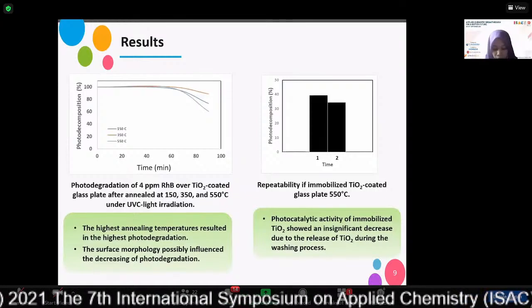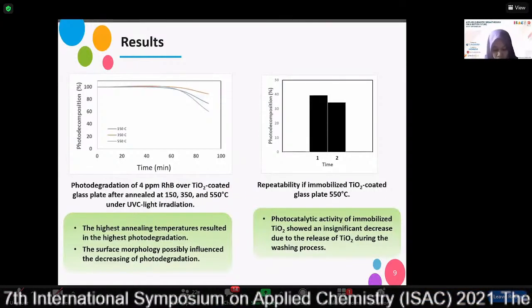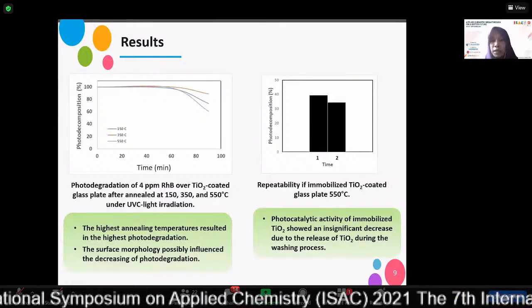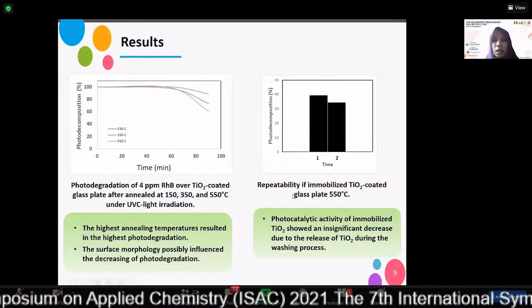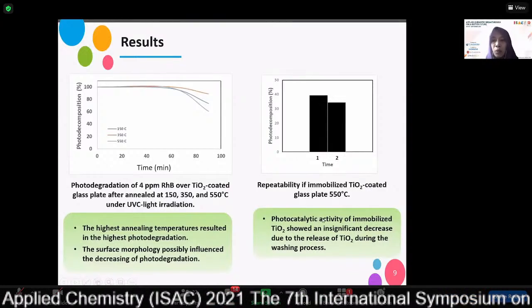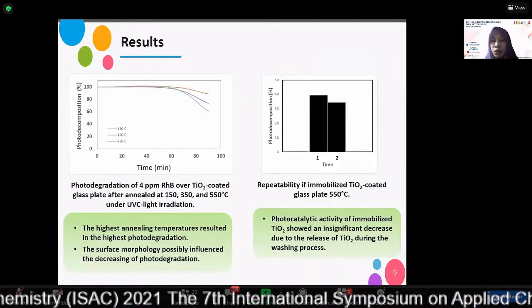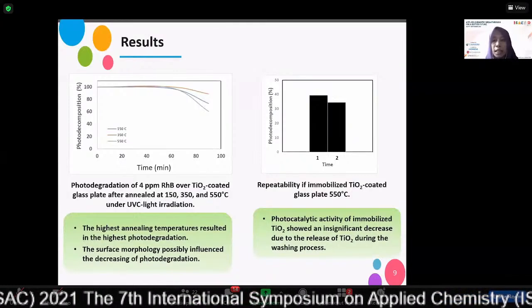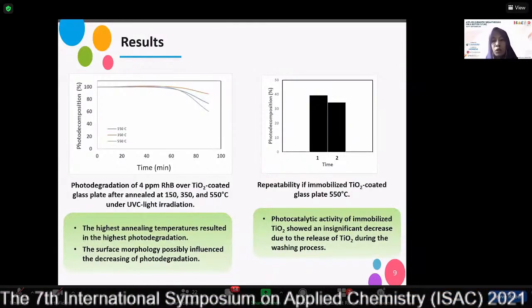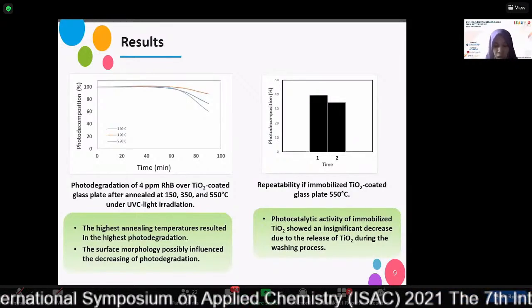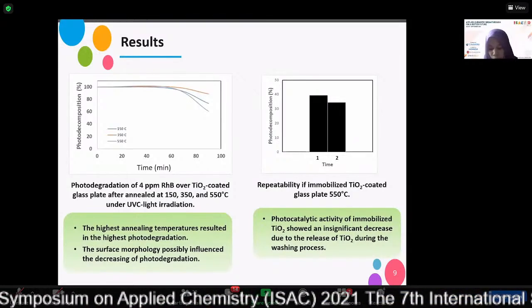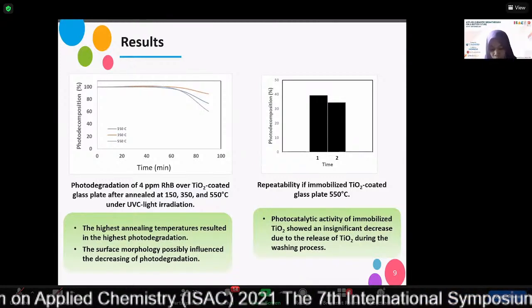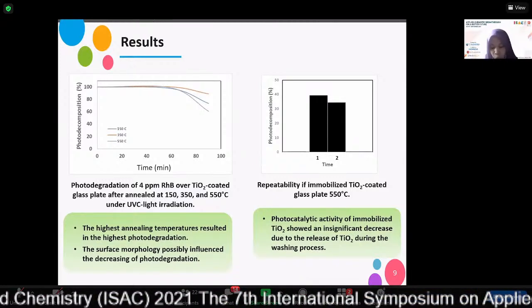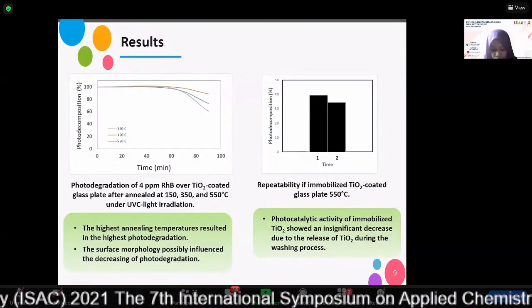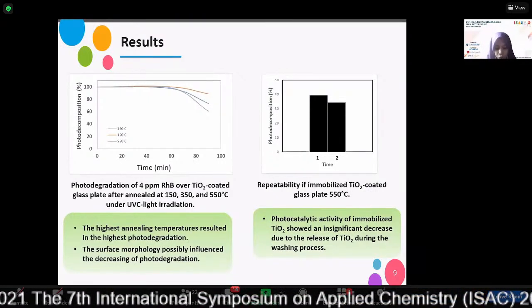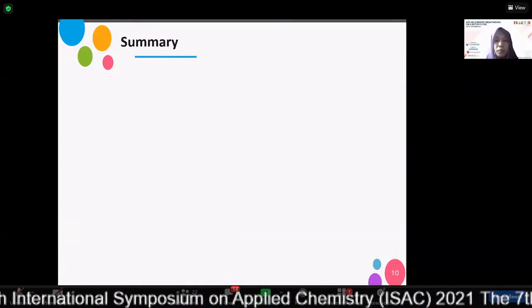And the consistency of immobilized TiO2, the repeatability of photodegradation, have been studied, and this is the result. It showed that the photocatalytic activity of immobilized TiO2 showed an insignificant decrease due to the release of TiO2 during the washing process. Here it can be concluded that immobilized TiO2 on the glass support simplifies the separation process after photocatalysis and could maintain the catalysis capability for repeated use.